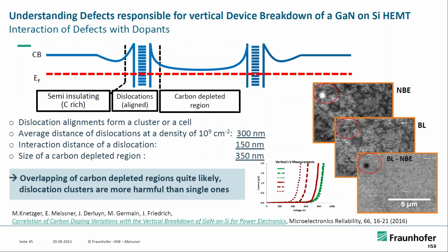If you measure this also in terms of the sizes of such spots, and compare it to theoretical sizes of strain fields, you find that even between two dislocations, the carbon-depleted region is even more depleted, so it's getting even more irritant. So imagine that you need an insulating buffer, and you create some depletion of your compensating dopant, and then you find that you get this region more conductive than in the vicinity.